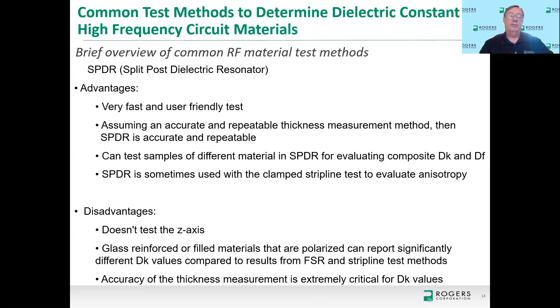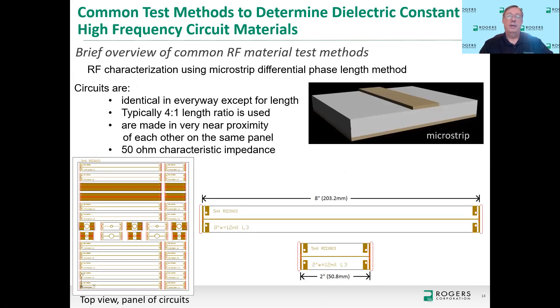The disadvantages of SPDR are that it does not test the Z-axis or thickness axis. It can have accuracy issues when testing glass-reinforced materials or materials with highly polarized fillers, and accuracy is highly dependent on how accurately you can measure the sample thickness.